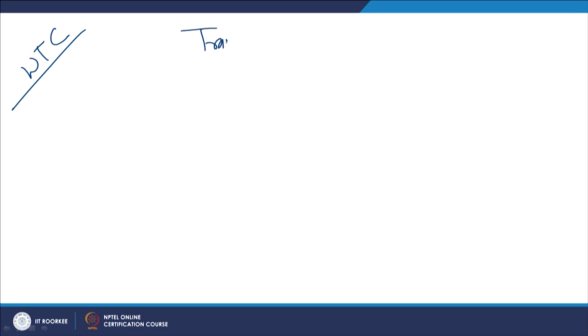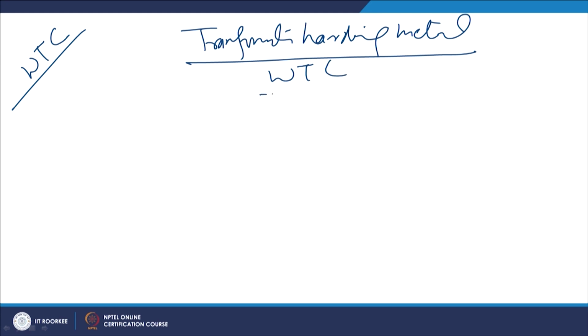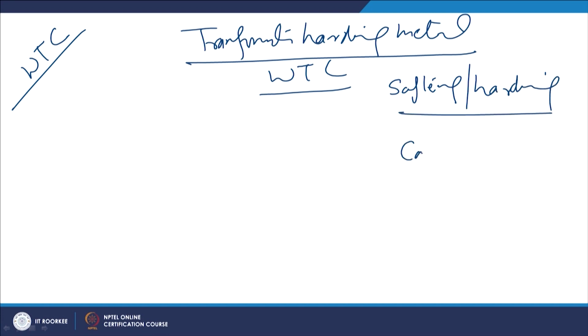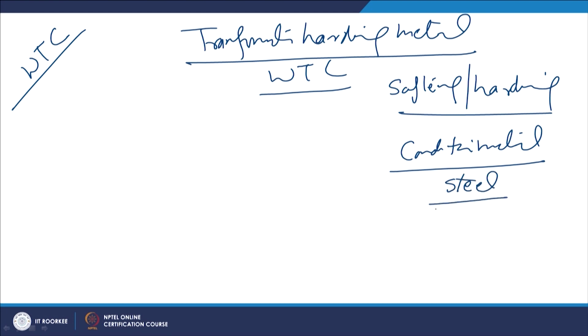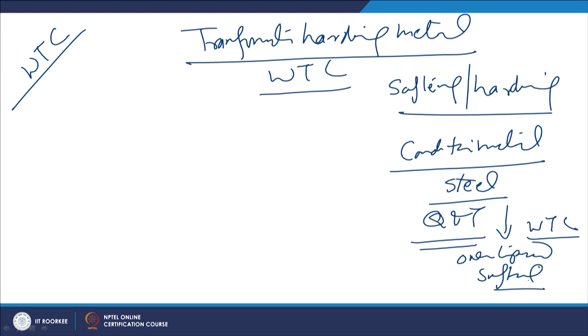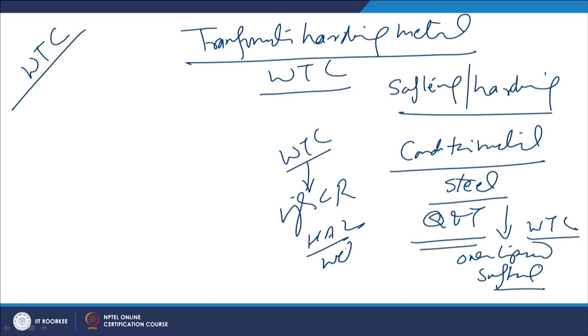So, due to the weld thermal cycle experienced by the weld metal and the heat affected zone, there can be softening or hardening as per the condition of the metal which is being welded. For example, if the steel is being welded in quenched and tempered condition, then after fusion welding, due to the weld thermal cycle in the heat affected zone, Q&T steel is over tempered and this leads to softening, while in most cases the higher cooling rate associated with the HAZ and the weld metal causes hardening of the metal.